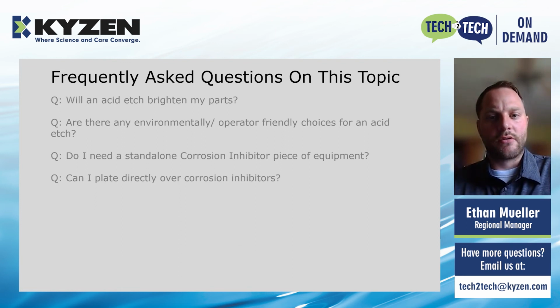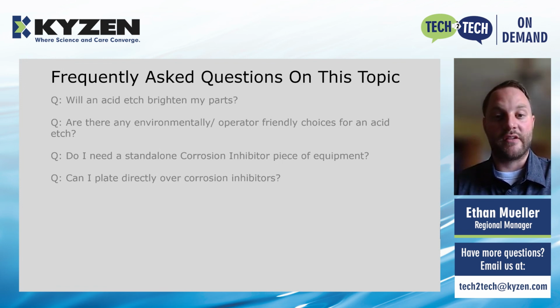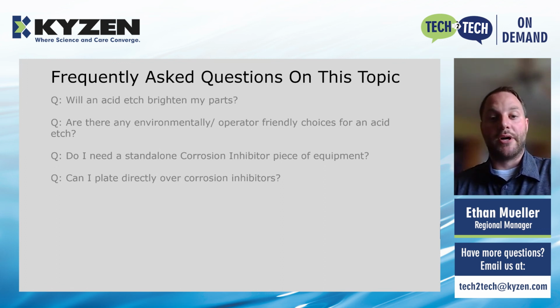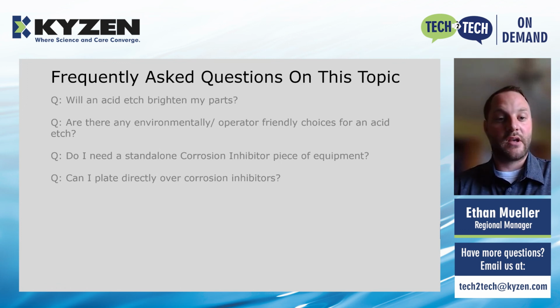Do I need a standalone corrosion inhibitor piece of equipment? No, generally, this is built right into your wash process. So when you go from your cutting tool to the washer, typically these inhibitors are going to either be built into the soap or the chemical that you're using to clean the parts, or you can add a standalone corrosion inhibitor to the rinse on your wash process. And so you don't need a standalone piece of equipment. They're out there. You could do it. It would probably look just like a dip tank with the corrosion inhibitor in there. And then you dip your parts in, take them out, let them dry, and the water dries away, and the inhibitor is left behind. But typically, this is built right into the wash process.